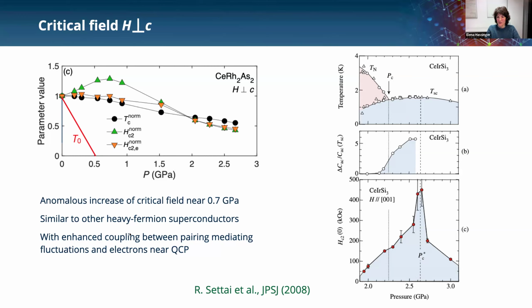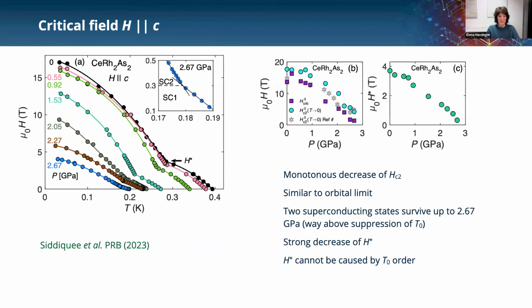So the way this is usually understood is that we have an enhanced coupling between the pairing-mediating fluctuations, which are unknown in our material so far, and the electrons near the quantum critical point, and this enhances the upper critical field. Okay, now the phase diagram along the z-axis looks like this. Here, TC is decreased again, as it should, and the upper critical field monotonically decreases.